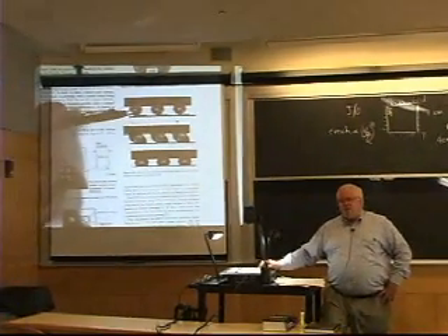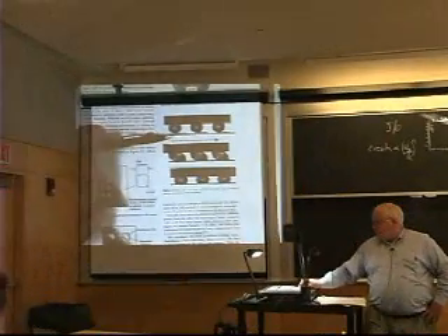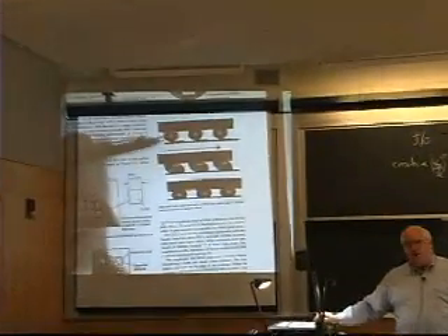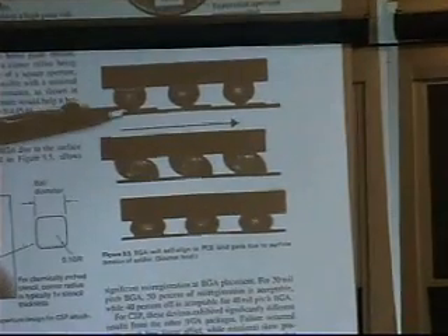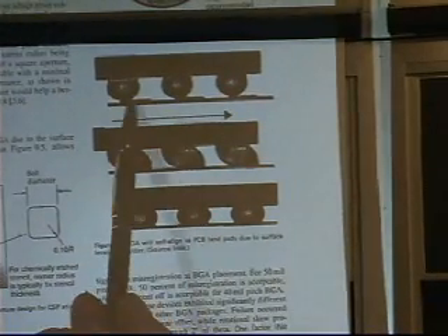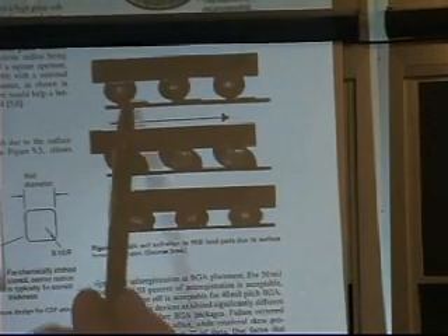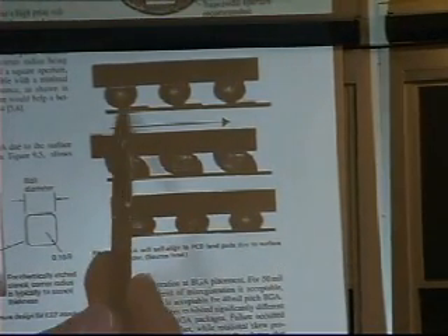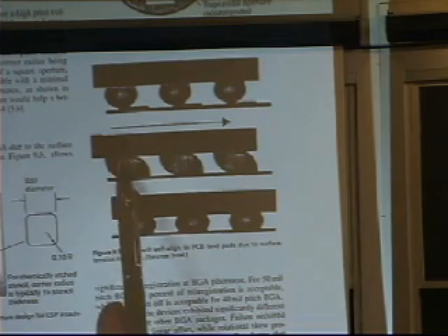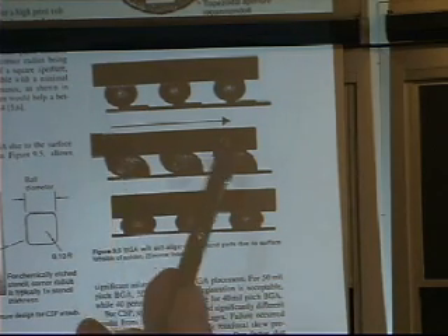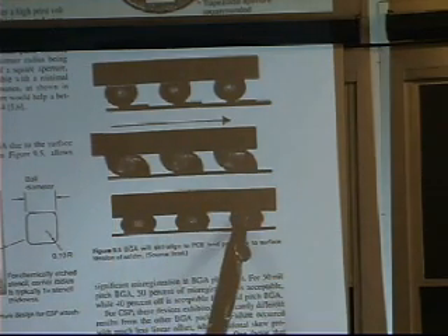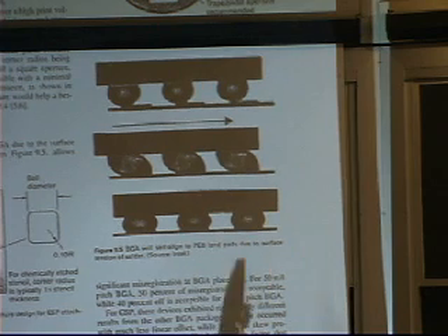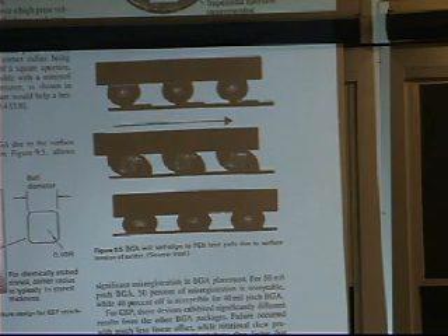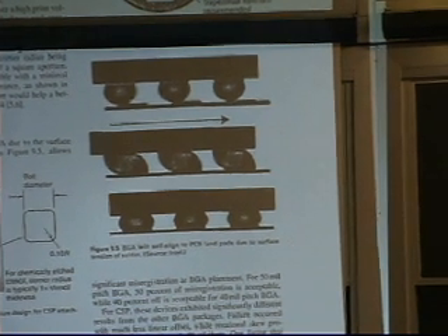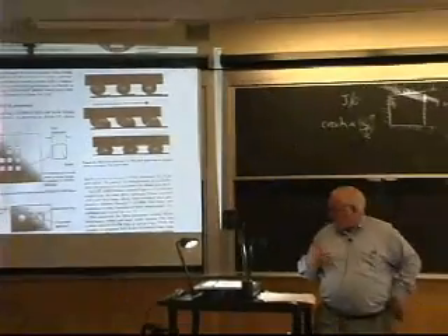One of the nice things about flip chip, as opposed to perimeter bonding, is that it's automatically aligning. Once you take these solder balls and bring them in here, and let's say this thing is off center, you see the pad is off center on the pad. If you actually melt it and it wets the surface, there'll be a surface tension that essentially provides a shear force, bringing this thing back into alignment. So it turns out you can make 1,000 bonds or 10,000 bonds, and things work pretty well.